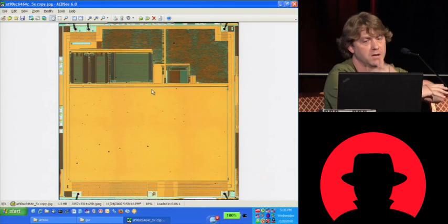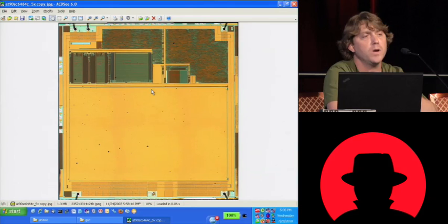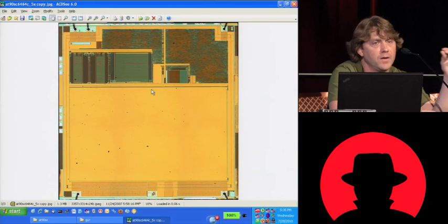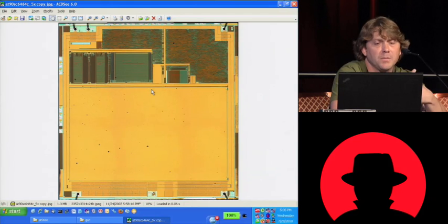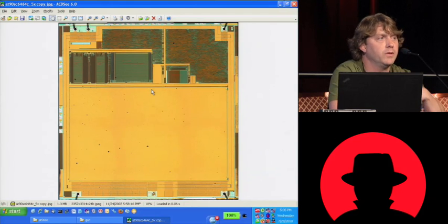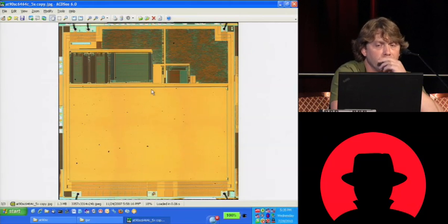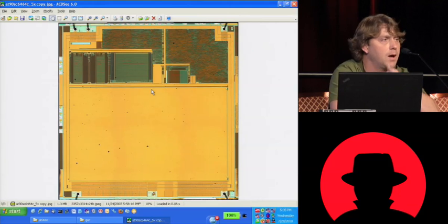We strip it layer by layer. Top metal, strip it off. Actually, one of them, you're going to leave it alone. Maybe you'll polish it down a little bit to get rid of some of the passivation. Sometimes the die will look clearer in your images if you mill it for a little bit on a lapping machine. Just lap it down a little bit. Remove a few microns of the passivation, that very top oxide.